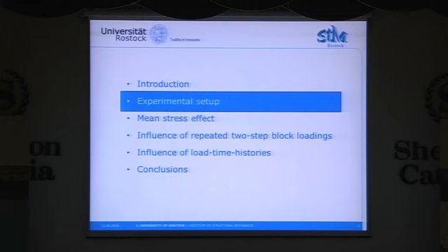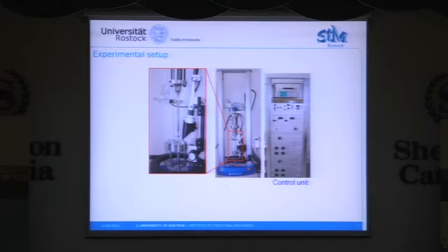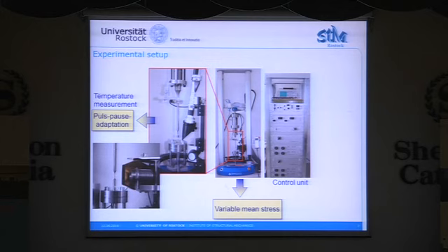So first I would like to show you our experimental setup, an ultrasonic fatigue testing system which has been developed at Vienna. And because Professor Stanzl-Tschegg already showed this experimental setup, I would like to show you only some points of it. At first, we also have a load frame in order to have the possibility for different mean stresses. Moreover, we apply a pulse-pause sequence in order to avoid the heating of the specimen. But we also cool, of course, the